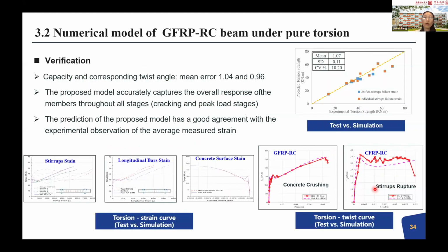So when we involve these two constitutive models and the governing failure mode coefficient, we can finally predict the GFRP RC beam under pure torsion, not only the capacity but also the complete progress during the loading. Even the stirrup, longitudinal bar, and concrete surface strains are quite close to the test.